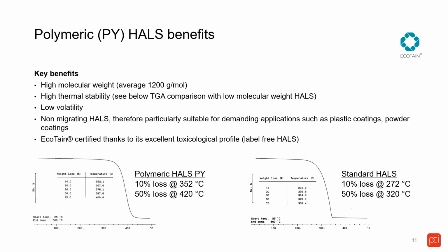The other factor to keep in mind when we talk about a polymeric HALS for powder coatings is that the HALS has to be soluble once you heat your systems and once you form your coatings, especially if it's a clear. Your HALS has to be soluble. So this is another factor to keep in mind when we talk about polymeric additives in powder coatings formulations. And this HALS actually was designed to be soluble.